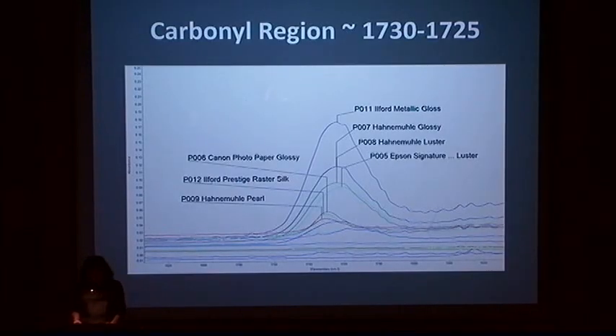In this detail of the previous spectra, we see only the carbonyl absorption band. The samples called out on the right have a carbonyl maximum at about 1720. This is an excellent agreement with the literature for polyethylene that has been oxidized by corona discharge. We also find in the patent literature for photographic papers corona discharge being the method used to improve the paper's compatibility with inks. Traditional adhesives might be viable for these polar RC papers.